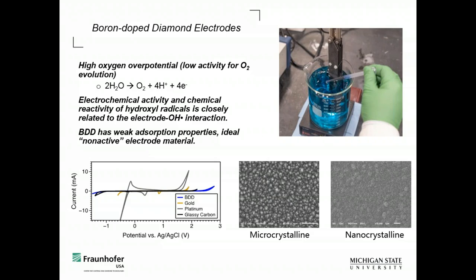But nonetheless, we have a lot of control over the growth process. So these are boron doped diamond films. Each one of these in this microcrystalline film, these are individual diamond grains that you can see here. This is a very dense coating, about 5 to 10 micrometers thick on primarily metal niobium substrates for this application. But we can also make nanocrystalline diamonds. So this scale bar here is 1 micron, this is 5 microns. You can't even see the crystallites here.